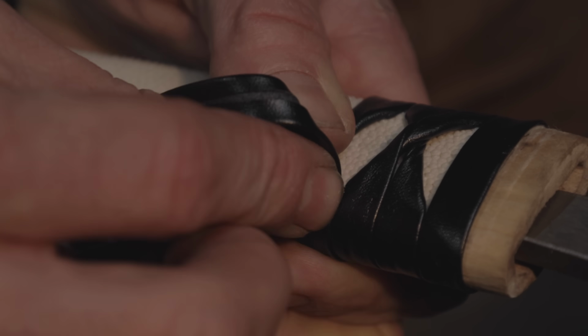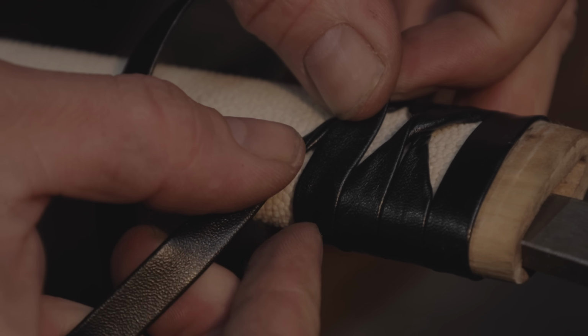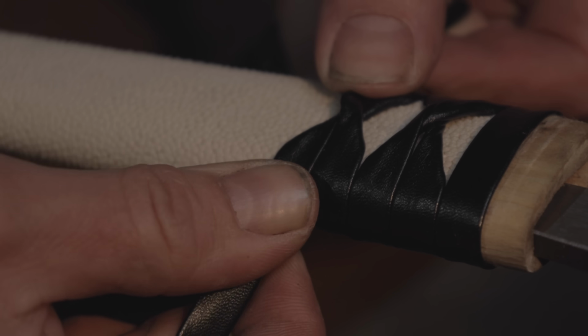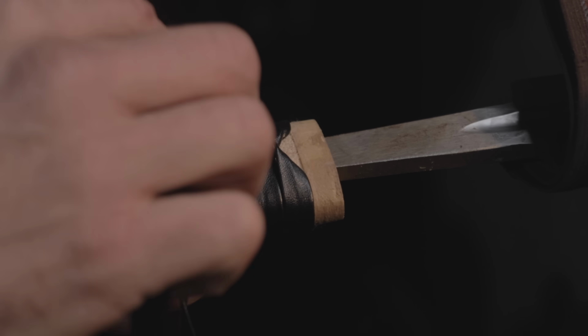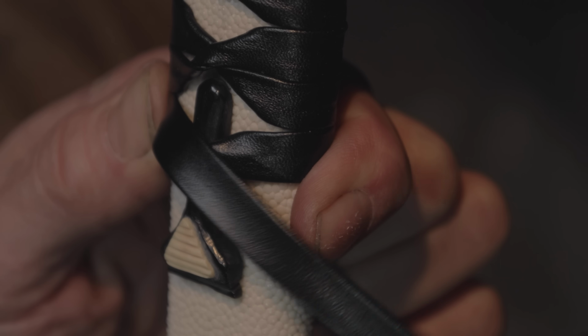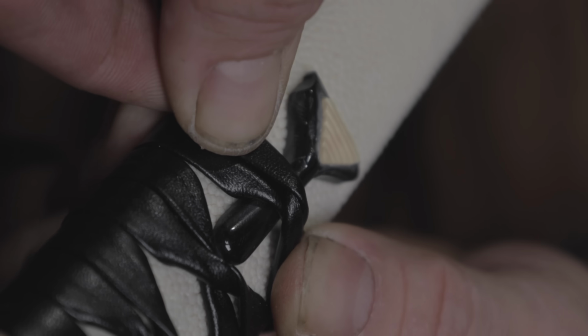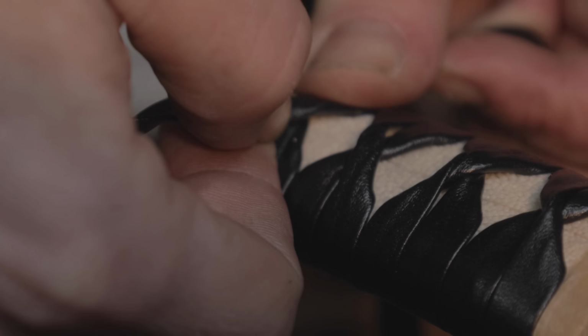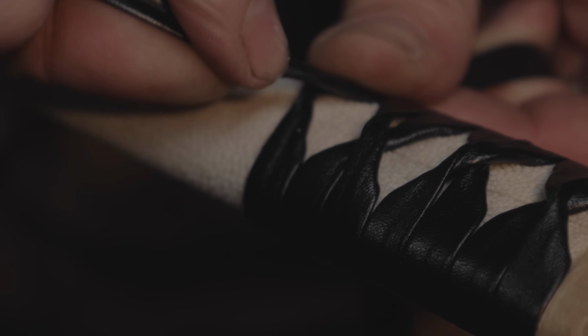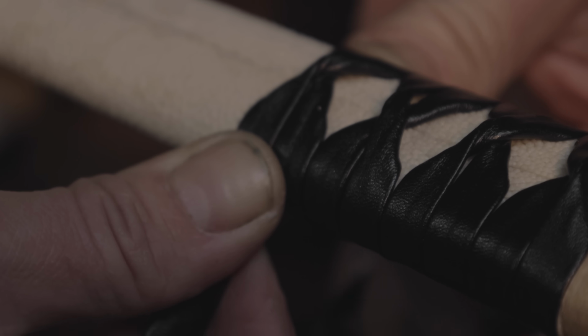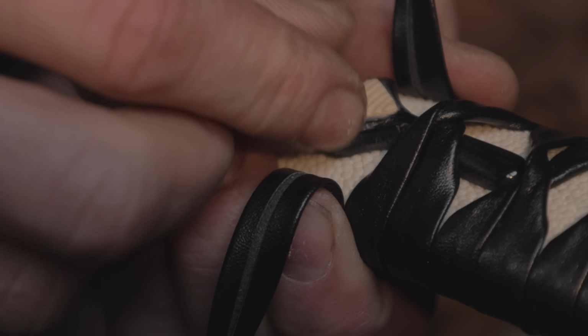The process was in no less way frustrating and difficult, and there's a lot of responsibility making something from unknown material, especially if that unknown material was cooked by me. But in the end, we got ourselves a katana. Some of the features of the home-cooked steel katana: once again, the hamon line, the border between the heat-treated steel and not heat-treated steel, was not as bright and well-defined as with a traditional steel, but that's not a big deal. That was to be expected. Another thing is the steel didn't like to forge weld as well as a traditional steel. Once again, that is only to be expected if one of your starting points is modern razor blades.